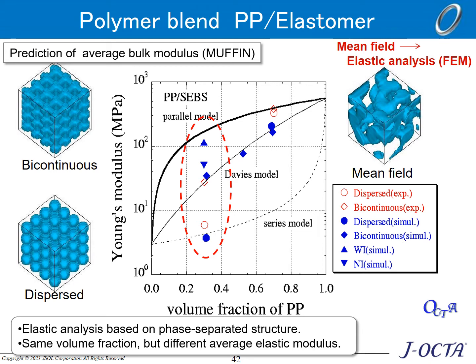We can see big differences among the structures. The circle is a dispersed structure, the diamond is a bicontinuous structure, and the triangle is the structure obtained by simulation. The important point is that each system contains the same volume fraction of components. The difference in average modulus is due to the phase-separated structure only. We can optimize the phase-separated structure to obtain appropriate properties.